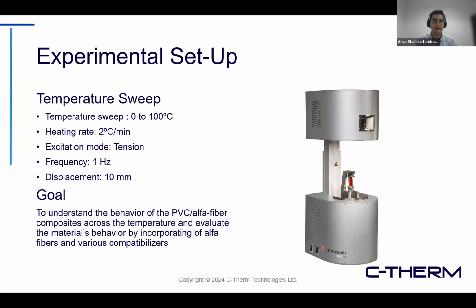So the experimental setup is explained here. The instrument was a DMA 50 Newton that is used for this test. The test is a temperature sweep from 0 to 100 degrees C, heating rate 2 degrees C per minute. Excitation mode was tension, and this test was run at a frequency of 1 Hertz with a displacement of 10 millimeter. To understand the behavior of these composites, they wanted to understand how the material behaves as they add more of the fiber along with different compatibilizers. So these are the results.